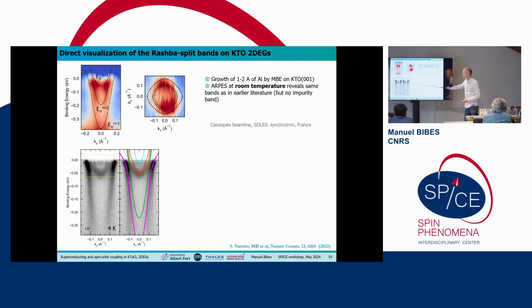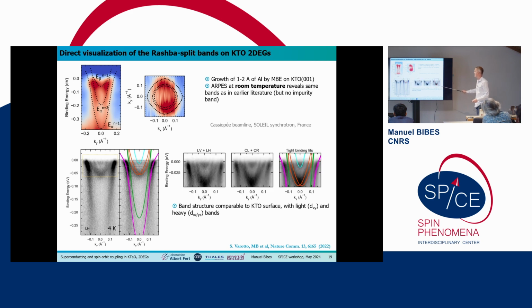If you do some further analysis, you can also see a little bit that there is another one here. And then there is some spectral weight here, which I'm going to show with higher magnification. And if you have good eyes, you can see there are actually 2 bands here and 2 bands here, which is consistent with a pair of Rashba split bands.